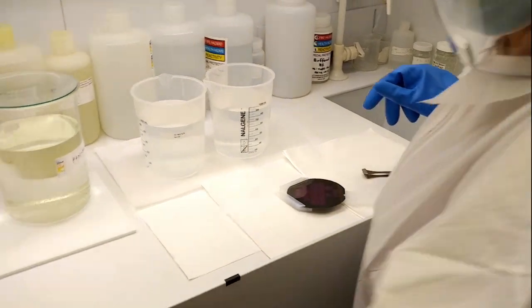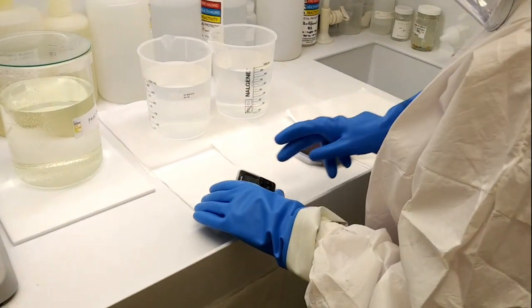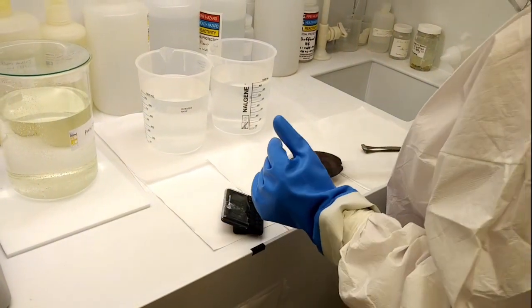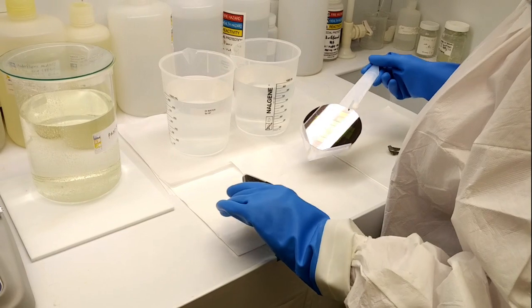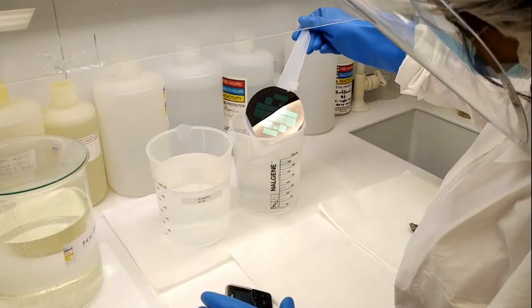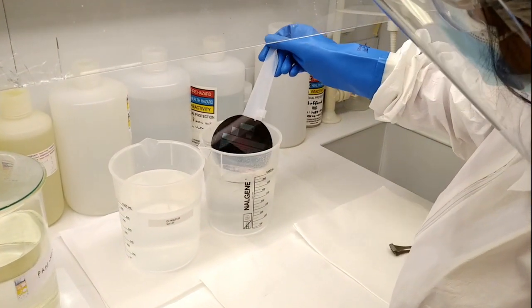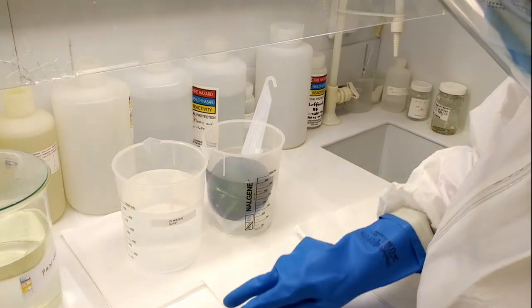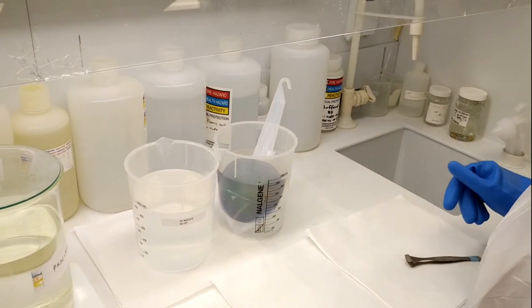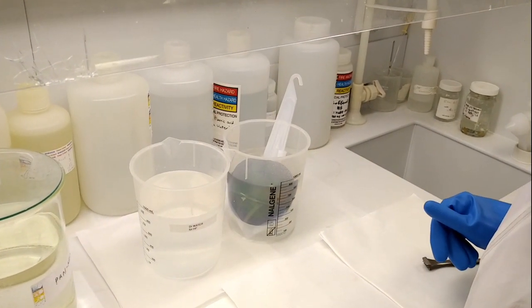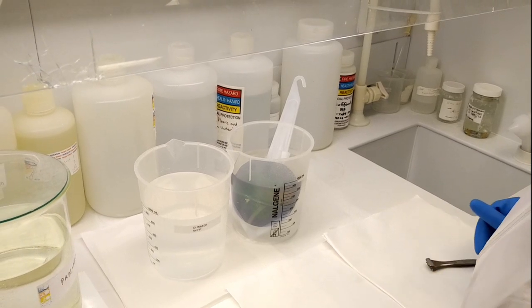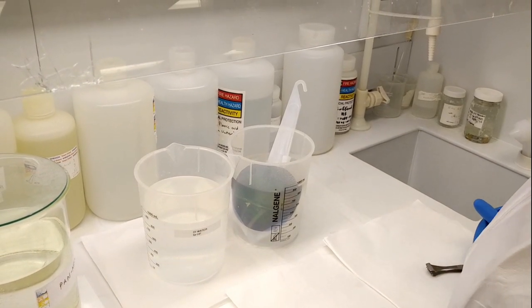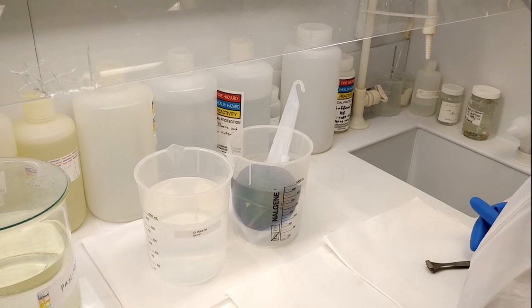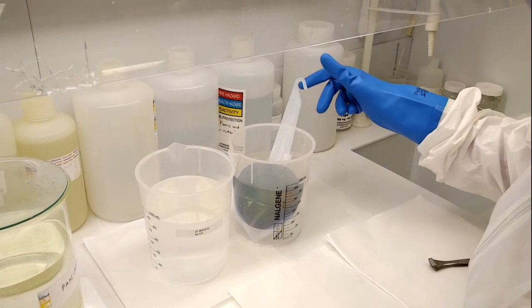It is also important to note the silicon oxide removed by hydrofluoric acid is essentially glass. Therefore, glass beakers cannot be used in this process, as they will also react with the hydrofluoric acid. The processed wafer is placed in a holder so it can be safely dipped in the hydrofluoric acid solution. The wafer is dipped in the HF and a timer is started to verify the etch rate, which can predict when the etching will be complete. The etching is stopped by dipping the wafer into deionized water.